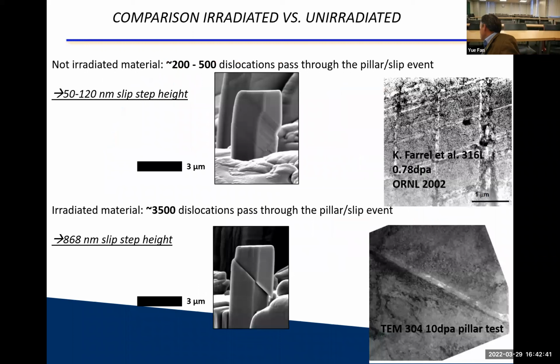And I do that, then I calculate that in the non-irradiated material, I see a slip step height of maybe 50 nanometers, maybe 100 nanometers, depending on which one you pick. The load drops are a little bit different. But in the irradiated case, I see 800 or 900 nanometer slip step heights, which is in correlation with what we see here in our SEM. So that's consistent. Now, why does that happen?